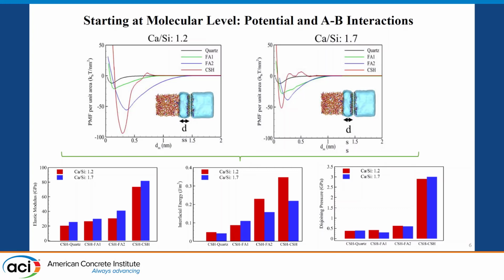So it means that the presence and concentration of cations in those fly ashes has an effect on how strongly CSH interacts. The larger the concentration of cations and alkalis, apparently our calculations show, the stronger the interactions become. The lower the concentration of those elements, the lower the interactions are. So there is a first idea that perhaps this will be responsible for the lower compressive strength at the early ages, and for the relation with the chemistry.